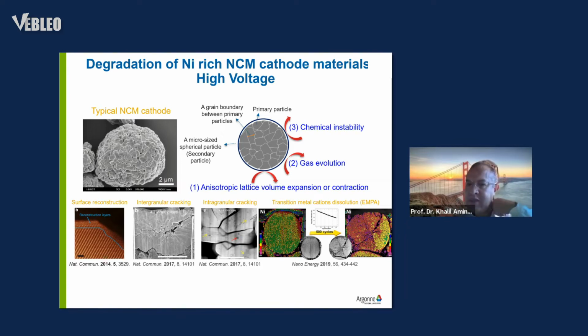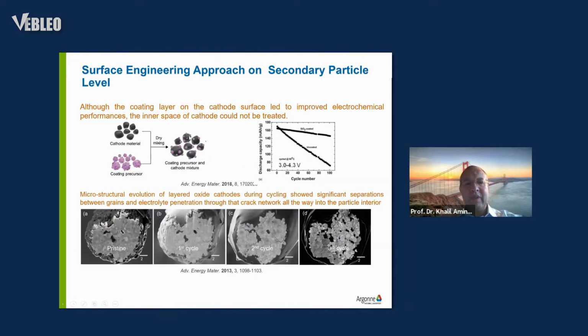It's almost impossible. You can see that clearly. When you do the coating, you get this type of particulate. At low voltage, you can get some performance enhancement, but at high voltage, you still have significant cracking, as you can see here. So this cannot be overcome when you go higher in voltage.